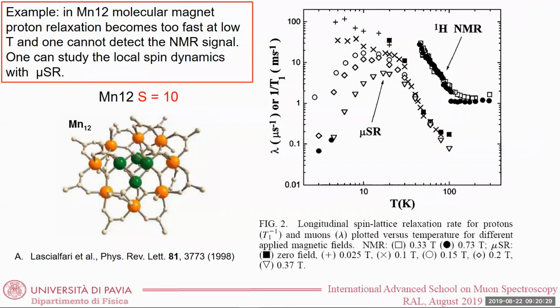So we started to study this system with NMR, okay, in particular with proton NMR, since you have plenty of protons here. And what you have if you do NMR is that you can measure the relaxation rate, so the 1/T1, the spin lattice relaxation rate, down to a certain temperature. But then you lose the signal because this relaxation rate is too fast. So what you can do is then to come to, in this case it was done I think partly at ISIS and partly at PSI, to do MUSR.